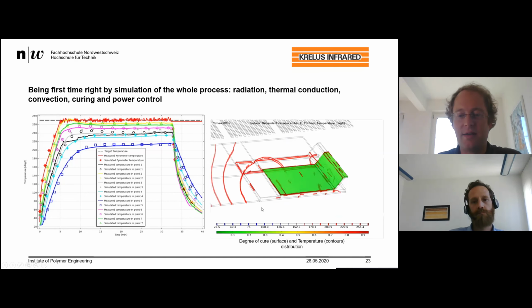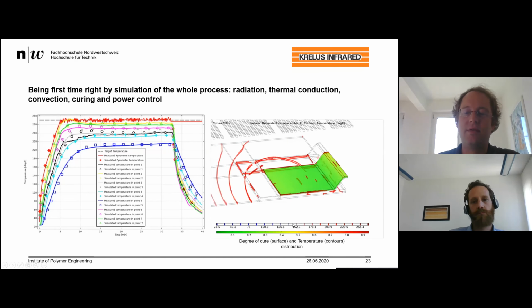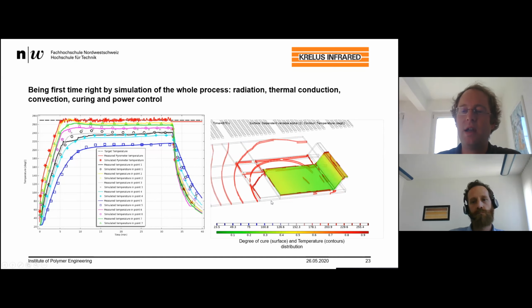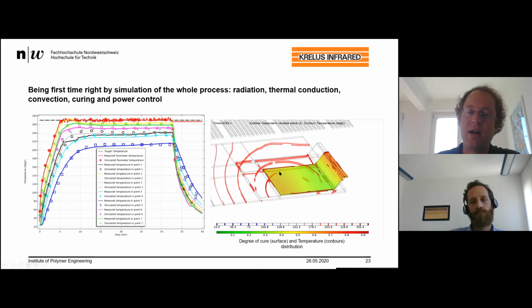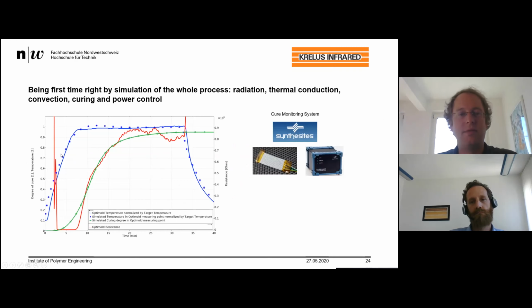So this is again kind of an animation of temperature contours and degree of cure, and you can see that the part cures homogeneously. The upper part is a little bit faster than this region, but related to the different distribution of the heating elements, I think this is a good solution. And then, as I said before, we also calculate the curing reaction from the temperature, and we are modeling the exothermal heat flow as well.